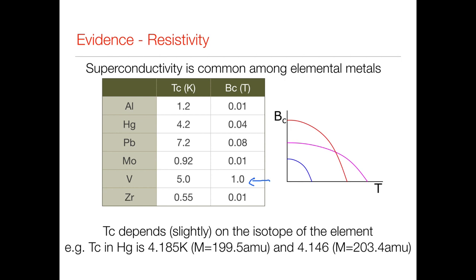Not by very much: 4.185 versus 4.146, so 4/100th of a Kelvin. You need a pretty good thermometer for that, but it's an effect, and it's been noted in other materials. So that's an interesting piece of experimental evidence that the transition temperature is somehow linked to the mass of the elements involved, not just the bonding.